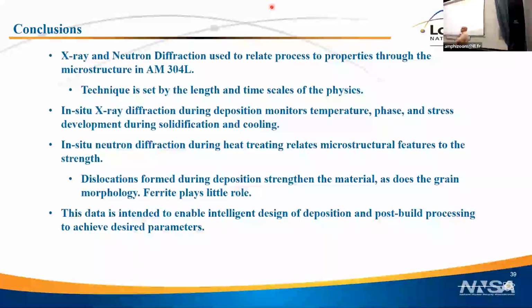I'm not exactly sure I understood the question, but what we did, and this is again something that's never quite made publication, we watched this material as we deposited it, which I showed. But then when it was all done and cold, we went back and mapped it in great detail ex situ. So then we could get the full 3D parameters and better quality data, and then make sure it's consistent with what we saw in real time as it was forming. I'm not sure if that answered your question or not.